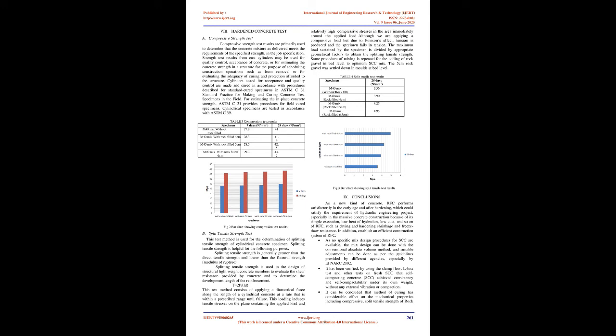Though the test is designed to measure flowability, the result is affected by concrete properties other than flow. The inverted cone shape will cause any liability of the concrete to block to be reflected in the result, if, for example, there is too much coarse aggregate. High flow time can also be associated with low deformability due to a high paste viscosity, and with high interparticle friction. While the apparatus is simple, the effect of the angle of the funnel and the wall effect on the flow of concrete is not clear.